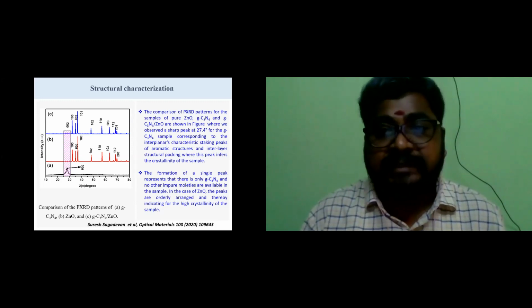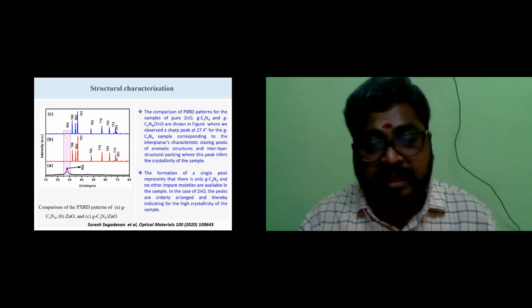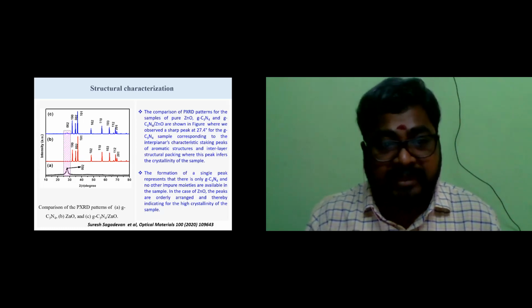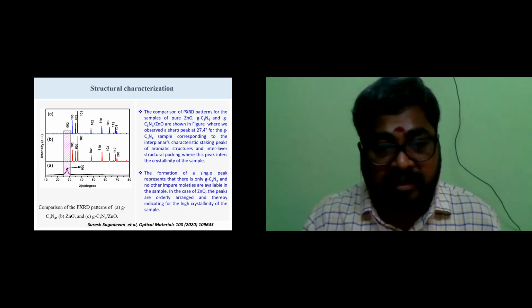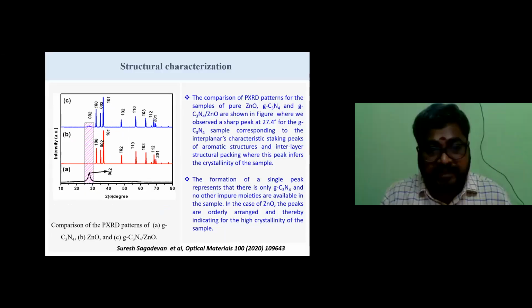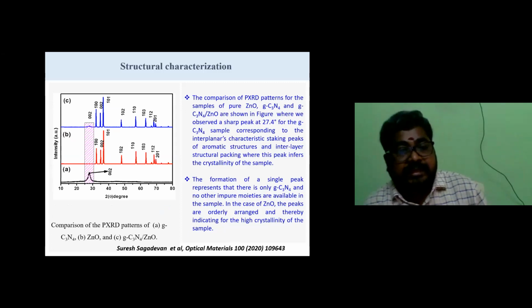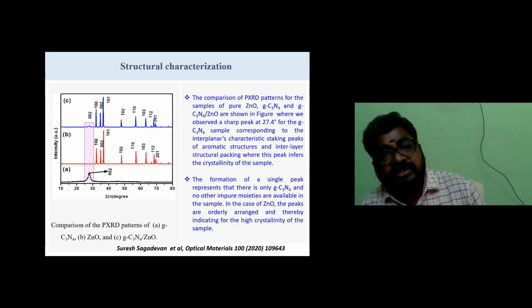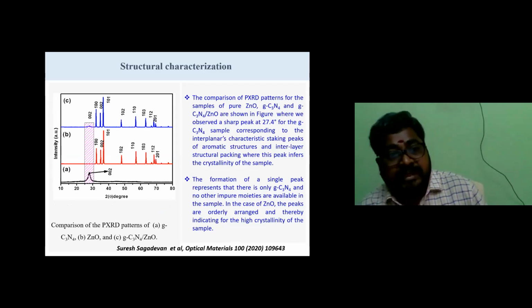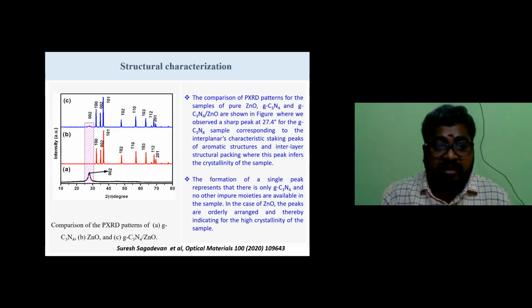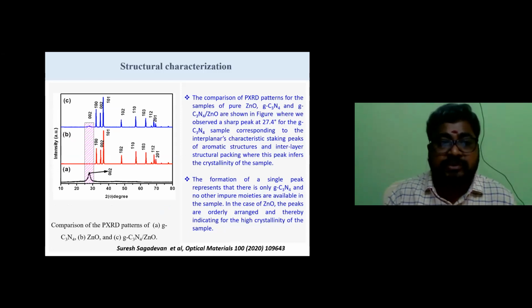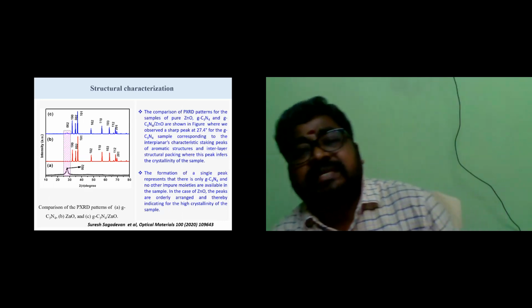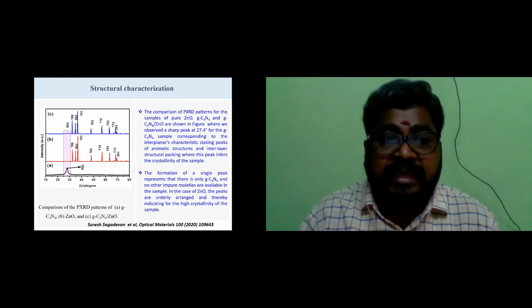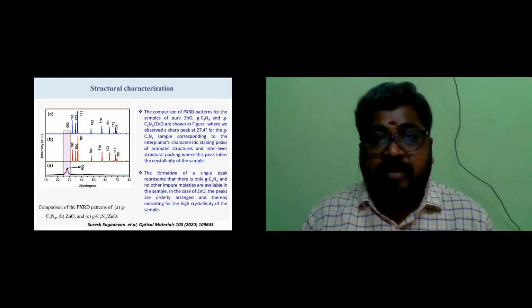So you can see here the comparison of our X-ray diffraction patterns. Figure A shows the XRD pattern of graphene carbon nitride. The plane is indicated by 002, and B is the XRD pattern of zinc oxide, and C is the composite XRD pattern. You can see here the 110 and 101 planes indicate the zinc oxide structure, and A's 002 plane indicates the graphene carbon nitride, and C clearly indicates that the 002 plane is present in this composite. So it is clearly stated that zinc oxide is incorporated with this graphene carbon nitride, which is confirmed by this X-ray diffraction.